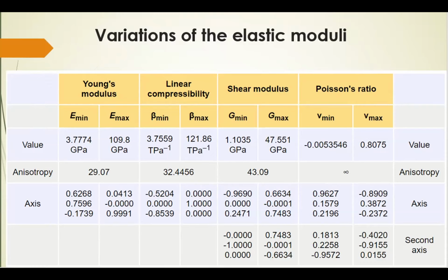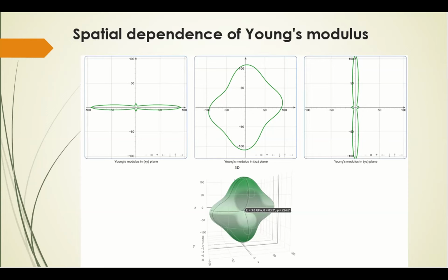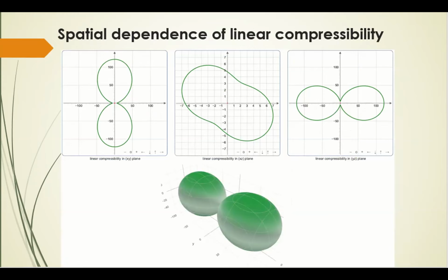These extreme Poisson's ratios are known to be characteristics of shape memory materials. Here we can see the spatial dependence of Young's modulus. It was between 4 GPa and 110 GPa depending on the orientation. It has the highest value for the 001 direction, about 110 GPa. Here we can also see the spatial dependence of linear compressibility. If this value is low, the material is harder, while if it is high, the material is soft. It ranges from about 4 per TPa to 120 per TPa depending on the direction.